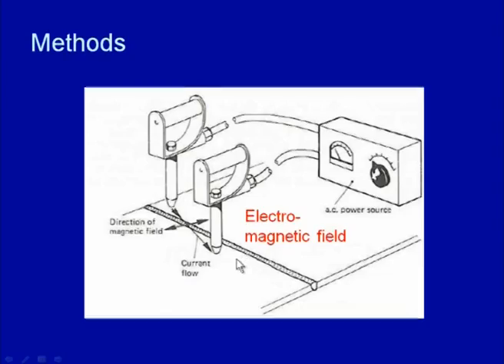Like this, these prods can be kept at different locations in order to have a magnetic field perpendicular to the discontinuities. But we know that when magnetic materials are magnetized, they remain magnetized even after removal of the magnetic field. So, they are sometimes intentionally demagnetized to avoid any adverse effect on the performance of the component.